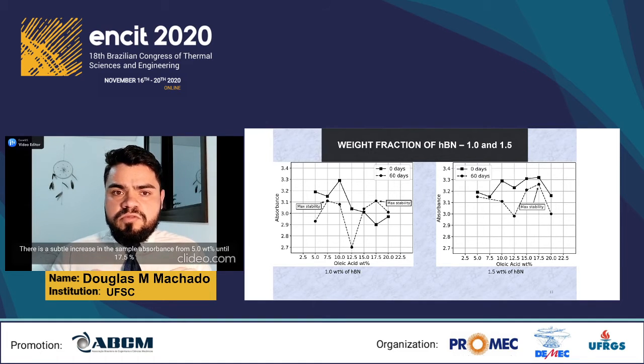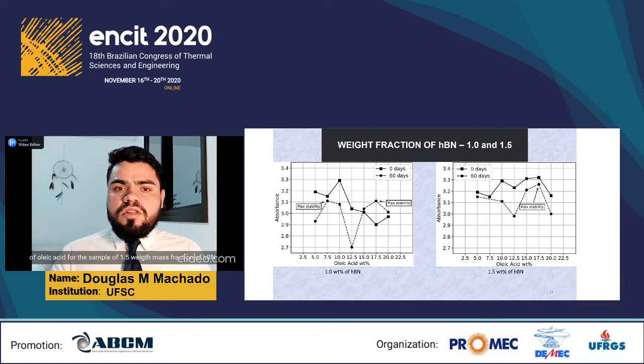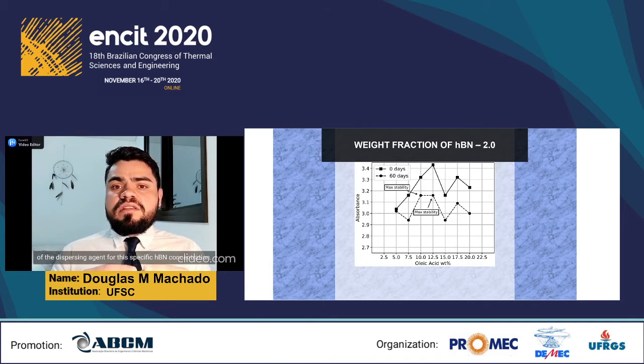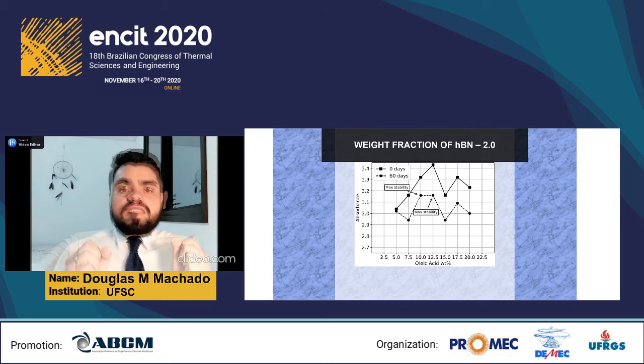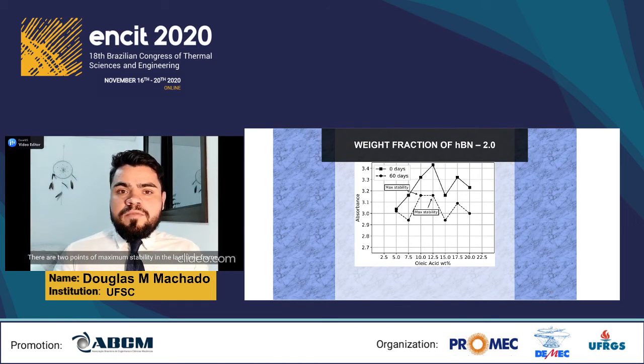There is a subtle increase in the sample absorbance from 5% until 17.5% of oleic acid for the sample of 1.5% weight fraction of hBN. From this point on, the absorbance decreases, suggesting the existence of an optimal weight fraction of the dispersing agent for this specific hBN concentration. There are 2 points of maximum stability in the last time frame, 10 and 12.5%.